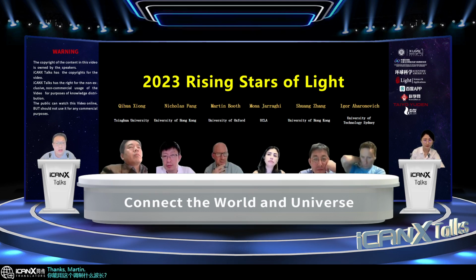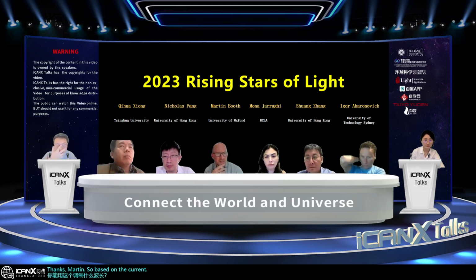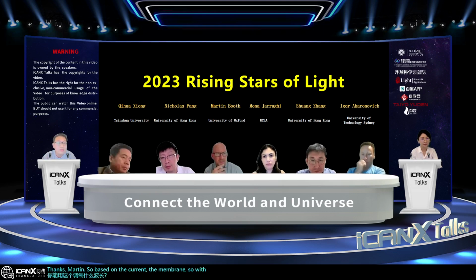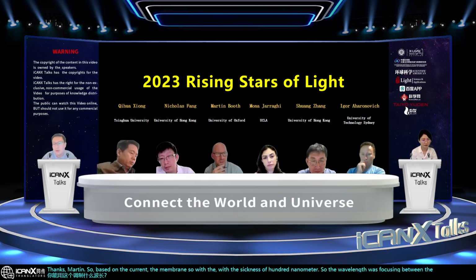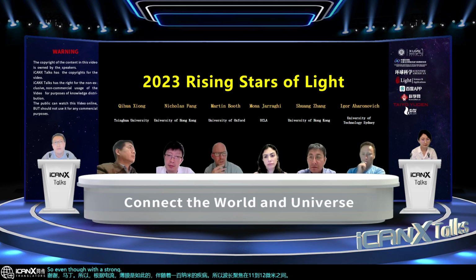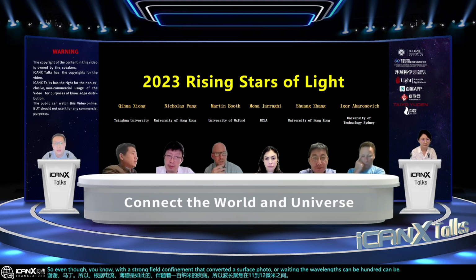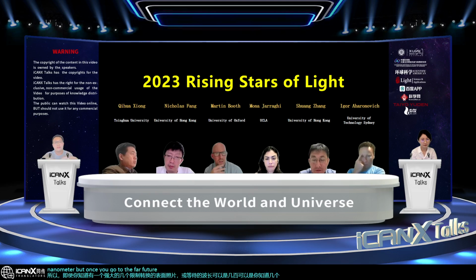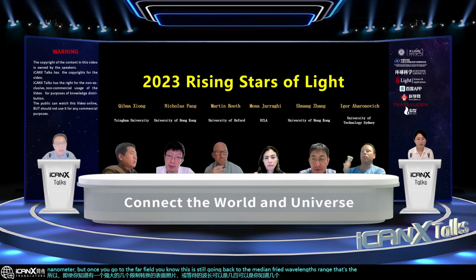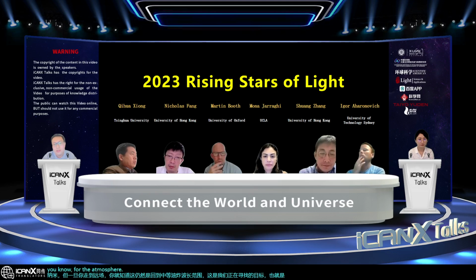Thanks, Martin. So based on the current membrane, with the thickness of 100 nanometers, the wavelength was focusing between 11 to 12 microns in the mid-infrared wavelength range. So even though, with a strong field confinement, the converted surface phonon polariton wavelengths can be a couple of hundred nanometers, once you go to the far field, this is still going back to the mid-infrared wavelength range. That's the target that we are looking at, which is transparent for atmospheric conditions.